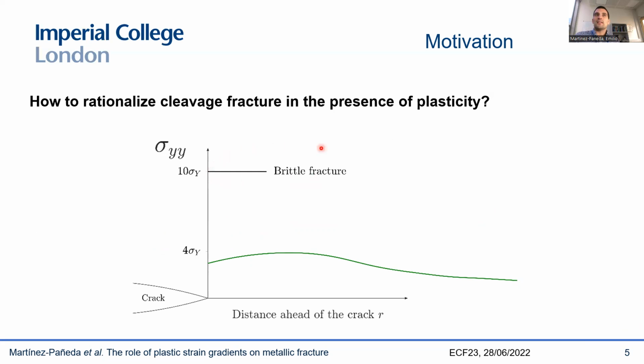Experiments are telling us that we are hitting this level, this brittle fracture threshold, but conventional continuum theories, when we do finite element analysis of stresses ahead of a crack, tell us that we're still very far away. So we are having stresses on the order of 4 times the yield stress. So what is happening here? What are we missing? How can we jump from here to here, basically? And our main hypothesis is that what we're missing in this picture is the role of plastic strain gradients and geometrically necessary dislocations. And the main motivation here comes from the experiments.